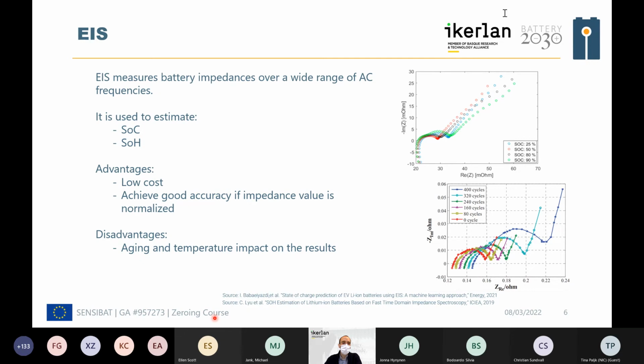In this case, the relation between the impedance and state of charge is not as stable as the SOC and OCV relation. The major problems are linked to the impedance change with the SOC, because it is not always sensitive.